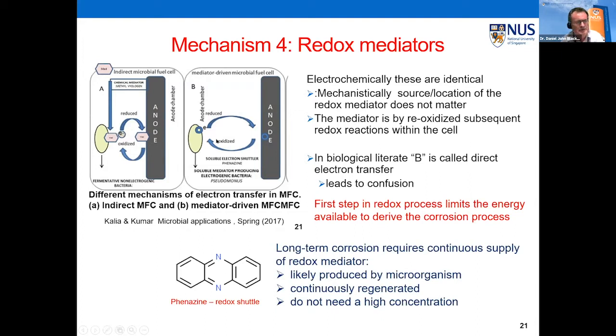And that leads to confusion, because if the species on the surface is some sort of redox couple, it's actually still a redox mediated process. And I could see that really in what Kerr presented, that a lot of what he's actually presented is a redox mediator that's bound on the surface. It's not the final product. If it was sulfate reduction, the final sulfate reduction takes place somewhere inside the cell, not on the surface. And that's what leads to confusion.